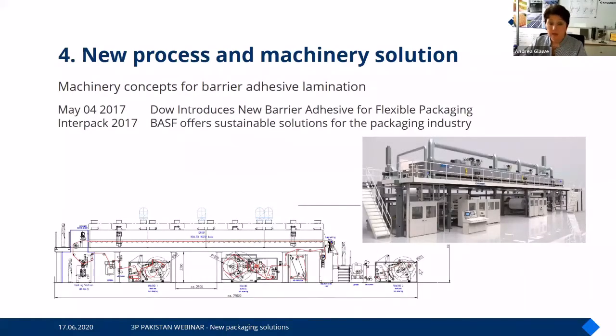Here you see a lamination line. I mentioned already that it's also a huge trend to laminate a PE film with a PE film with a certain kind of barrier adhesive in between. Dow is doing a lot of development, the company BASF, but also Henkel. And for that, you need at least a machine which is able to apply the adhesive film, which you see here with an engraved roller system. We have the drying equipment, and at the end, the second film is laminated on top of this sticky surface. And then you have very perfect laminated pure polyethylene material available.